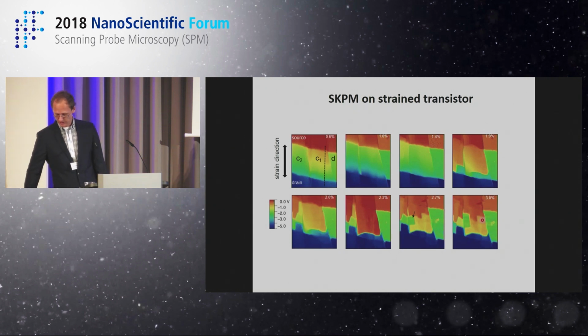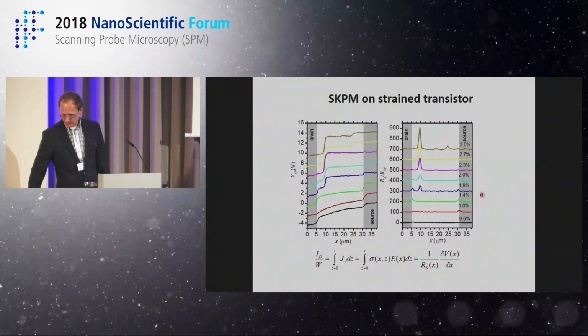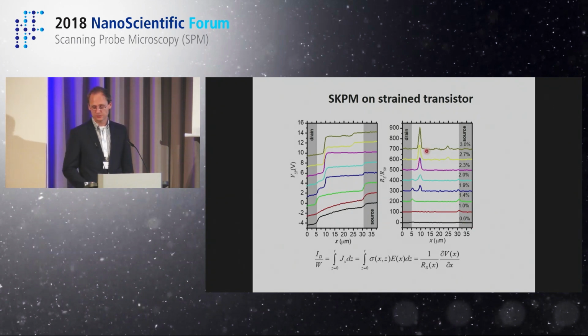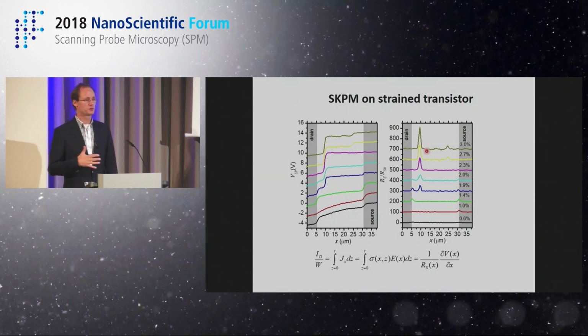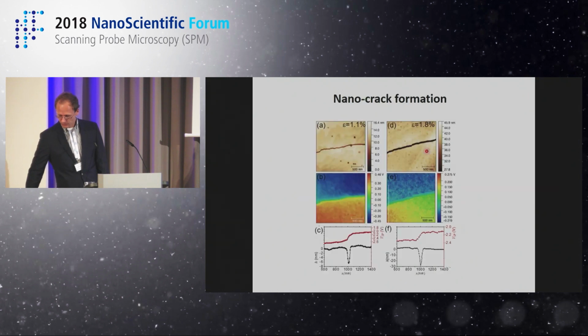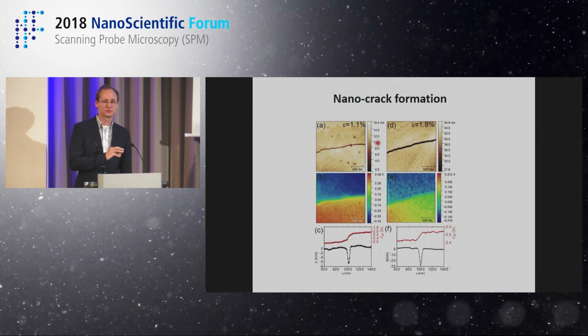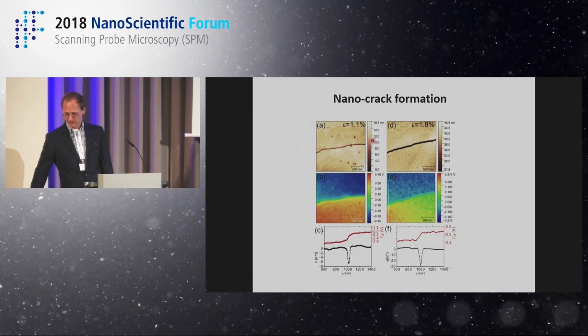Right, when I have this information, of course I can quantify it in more detail and have a look at local transport properties. Here you see how these barriers emerge at the contact, and then in the channel you can calculate a local sheet resistance for such a barrier, and you see that these barriers have transport properties that are orders of magnitude worse than the pristine, intact semiconducting crystal. If we now go again into morphology mode and look at a very close scale at what's happening at these barriers, we see the emergence of very small nano cracks in the crystal.